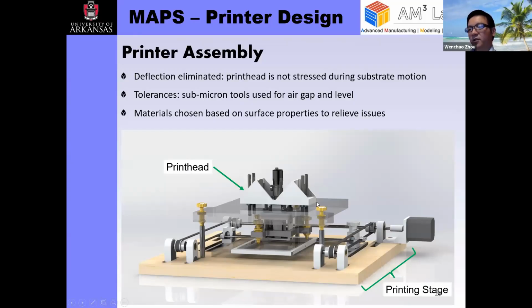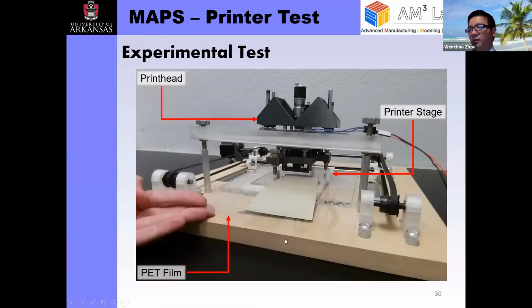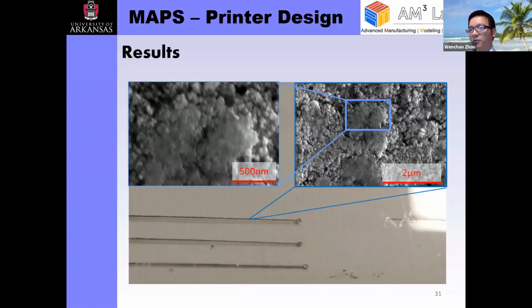a printer to conduct the printing tests, with this printing stage and printer head mounted here, and the micro heater is mounted here. We put a layer of silver nanopaste, a screen printing silver nanopaste on a plastic film, underneath the micro heater, and we activate that and move the printing stage. After it moves over, we wash off these unsintered particles, and we're left with a printed line.